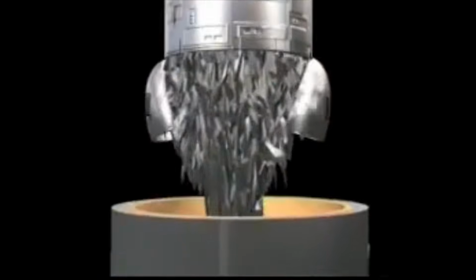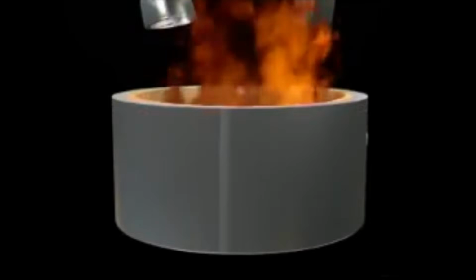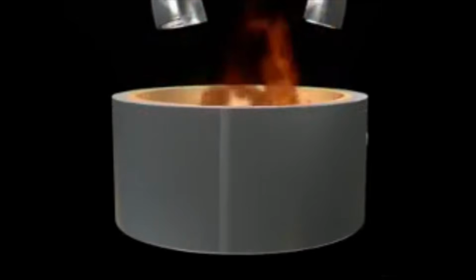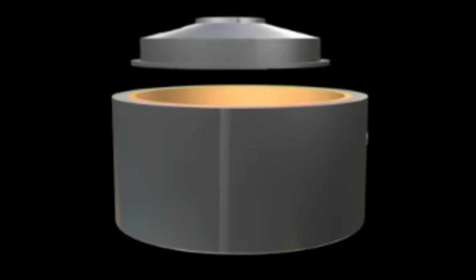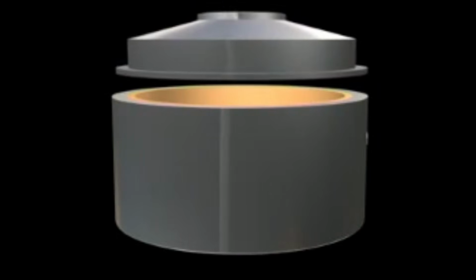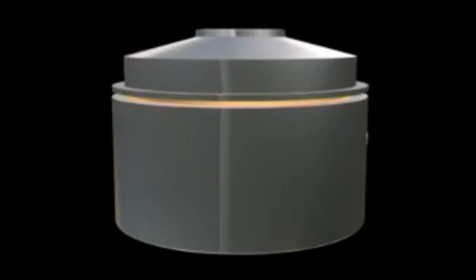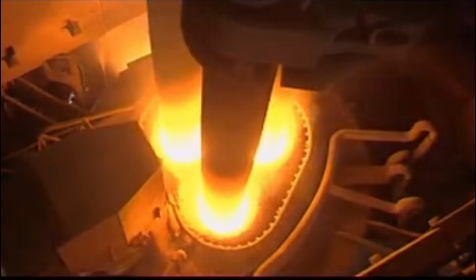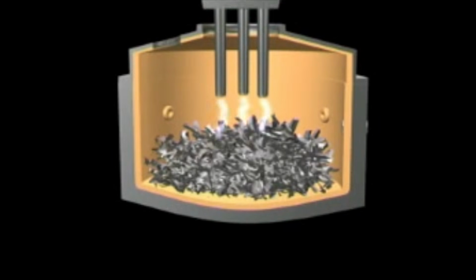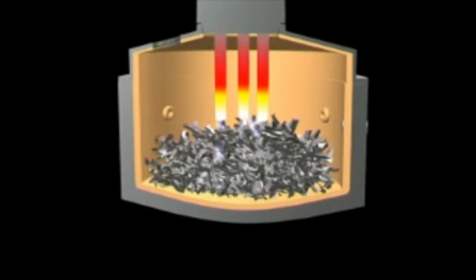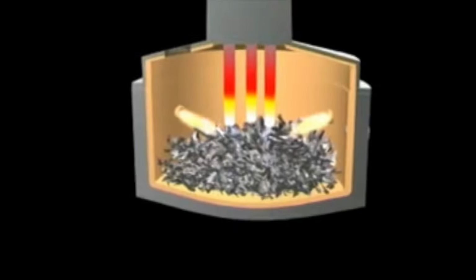To efficiently recycle the selected scrap and integrate it with the direct reduced iron produced in the previous stage, the steelmaking furnace is charged in 2 steps. The first step involves adding carefully selected scrap. These furnaces have a total charging capacity of about 105 tons. The scrap is melted and transformed into a uniform liquid bath through the combined input of electrical energy and the injection of oxygen and methane, which accelerate melting and promote oxidation of undesirable elements.